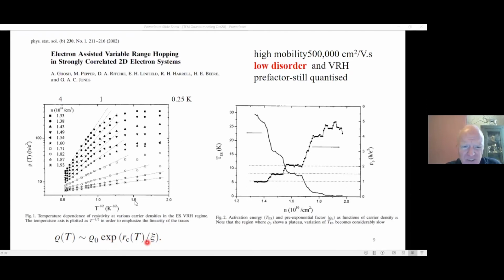What happens at very, very low temperatures is that the hopping distance gets very, very large, comparable to the size of the device. Once your hopping distance gets comparable to the size of the device compared to the localization length, things become independent of temperature as the hop distance becomes longer than the device. So at lower temperatures, the device switches off.